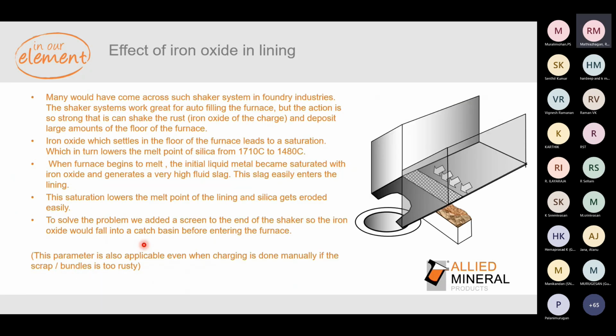So we come to understand iron oxide, because this is one thing which we always talk about to our customers. Nowadays, with technologies growing and automatic shaking systems coming into play for charging the furnaces, these shaker systems are strong enough that they segregate the rust and the scrap. Because of the vibration, whenever you charge the furnace, the iron oxide enters the furnace first, along with the scrap. It gets deposited on the floor and on the side walls of the lining, and the melting operation starts. The liquid metal gets saturated with the iron oxide, and it generates a lot of highly fluid slag, which easily enters into the working lining.